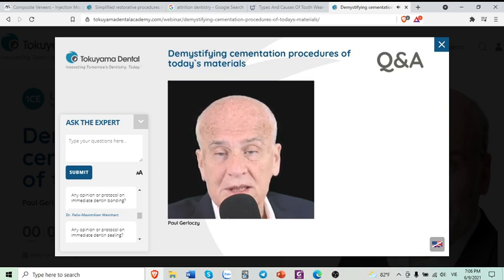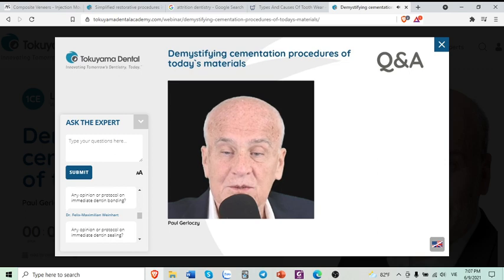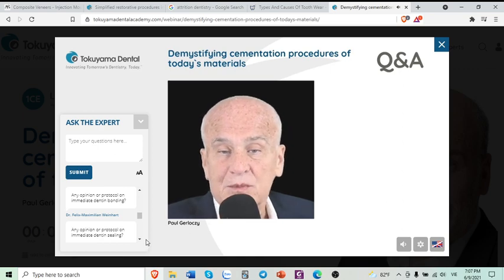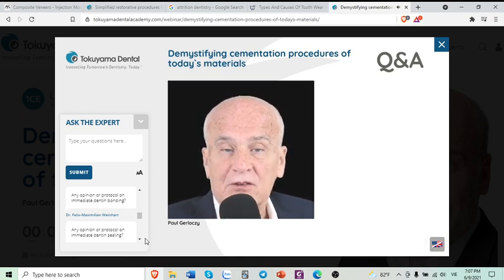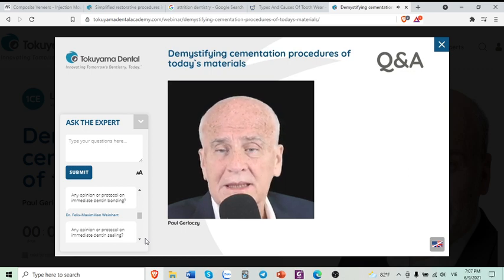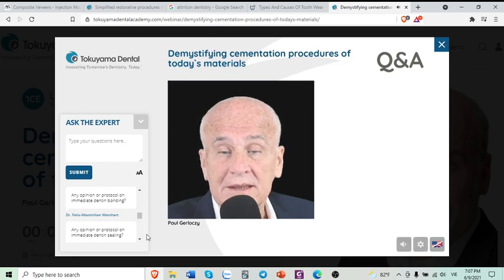What I do is I etch the enamel part again. And of course, before I do that, I will again freshen up this bond with sandblasting, but very, very gentle in this case. Okay, I hope that answers your question. But whenever possible, please use immediate dentin sealing, because there has been a lot of science behind that: you get a better bond if you seal immediately after you've cut the dentin, and not weeks later or days later when you're cementing and you may have contaminated that surface.